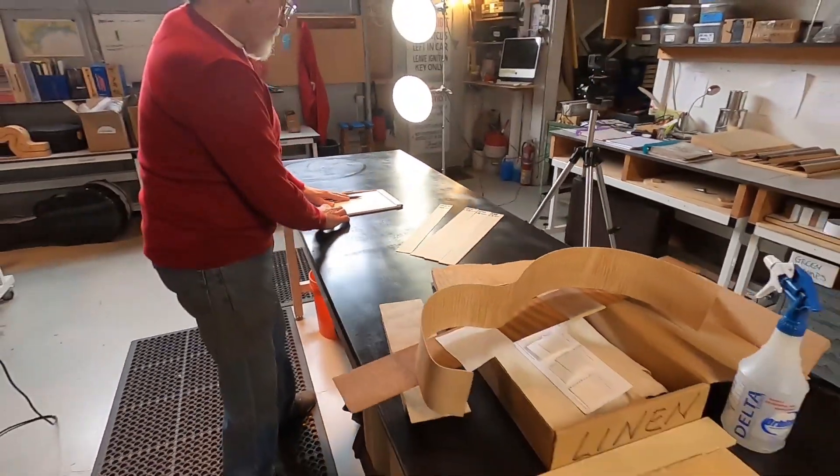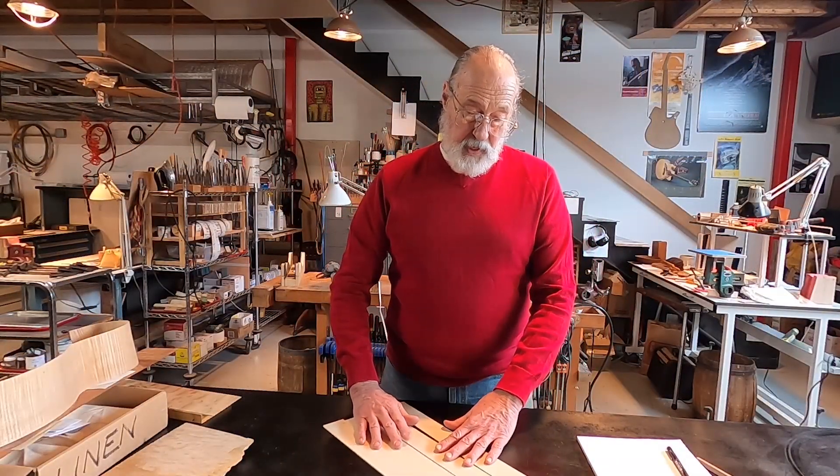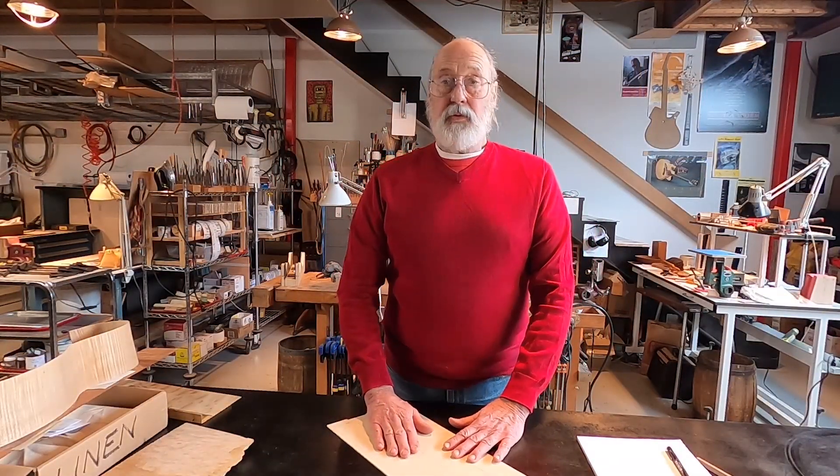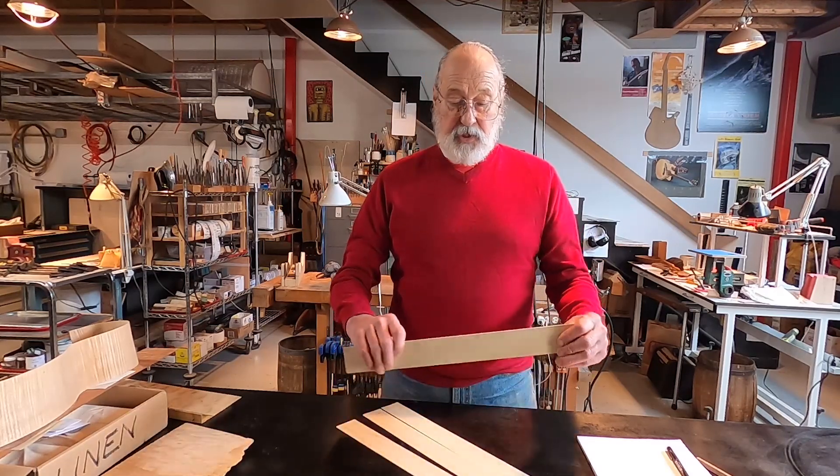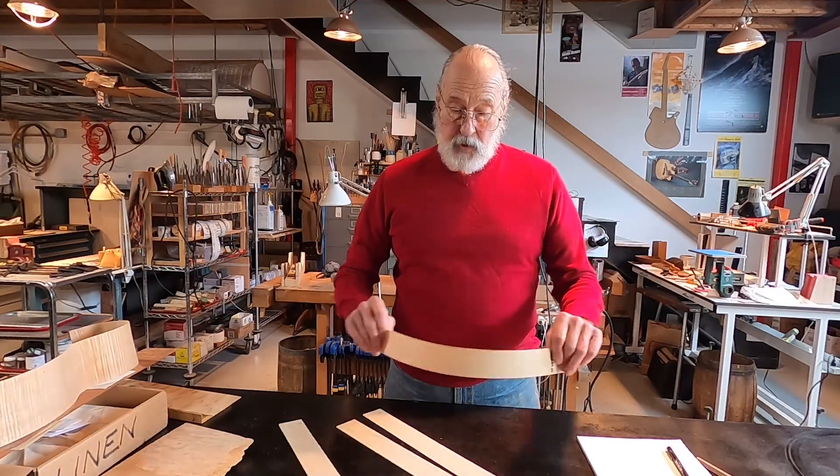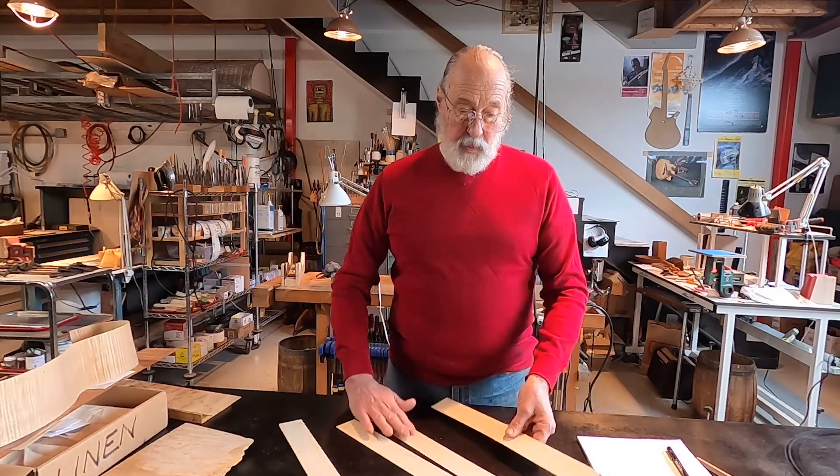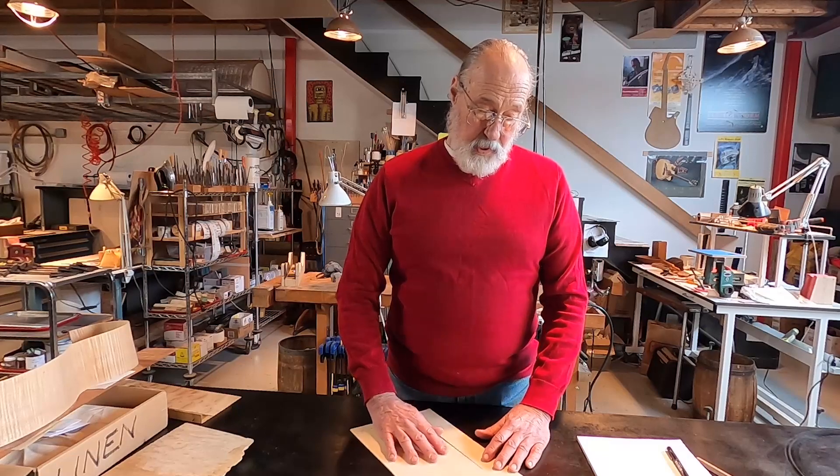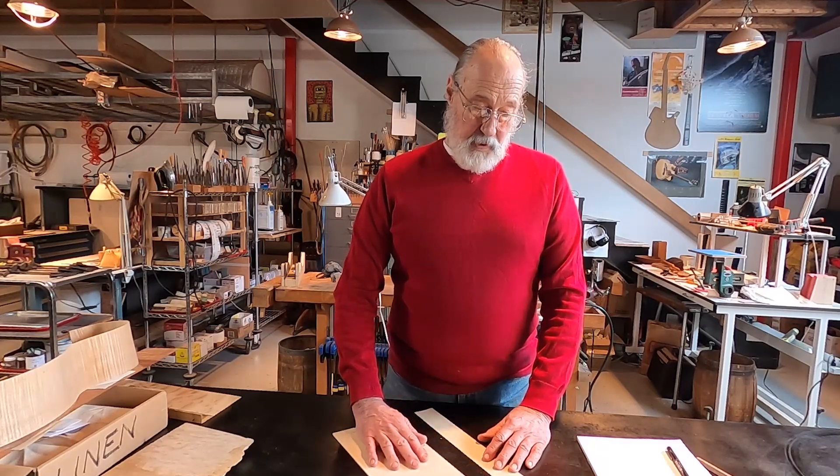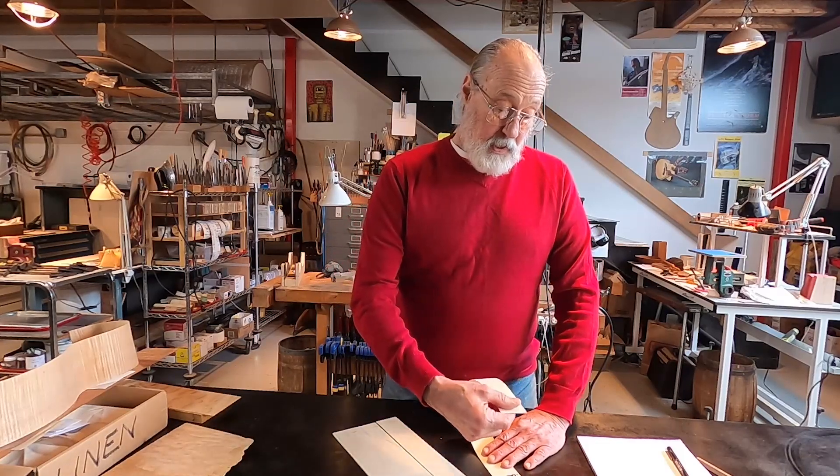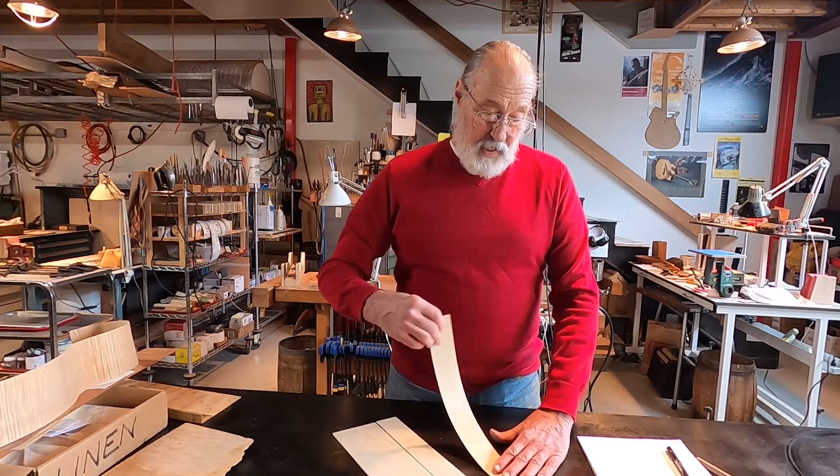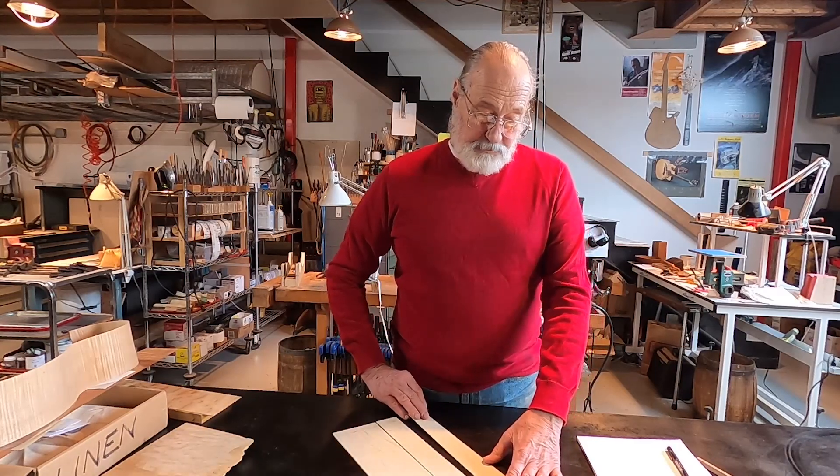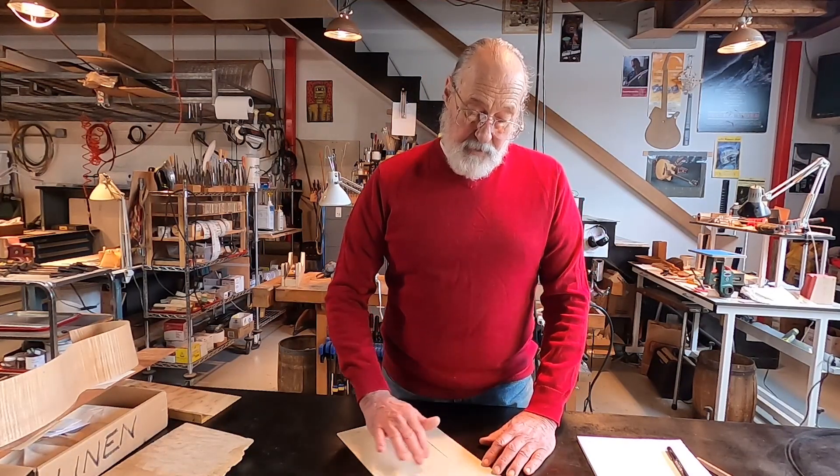I'm going to show you how I like to do that, but first let's talk about one more thing, and that is how stiffness of the wood varies with the thickness. We all know that a thicker piece of material is harder to bend than a thin piece of material. Everybody knows that. But maybe everybody doesn't know what the relationship is between those two things, and this is very important in guitar making or any kind of fine woodworking where you're trying to figure out how much strength you need, and in particular here, what you can get away with for bending. Now it turns out that the stiffness of a piece of material varies with the cube of the thickness of the material, all other things being equal.